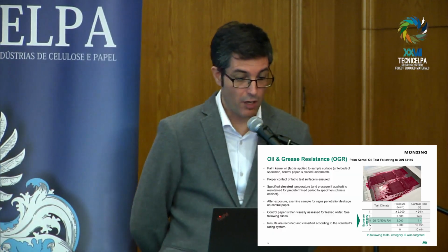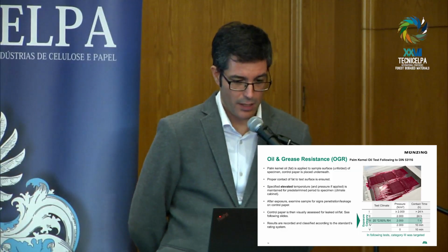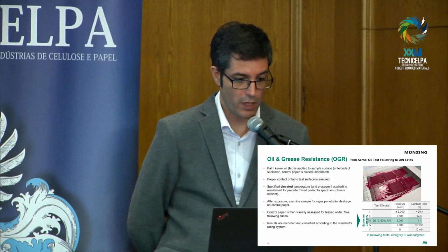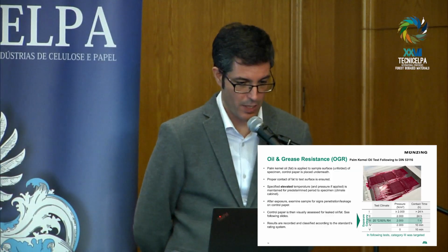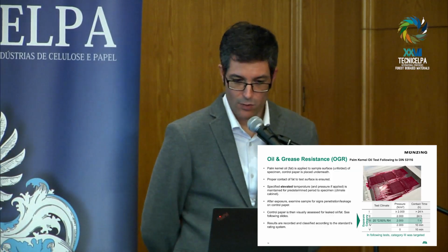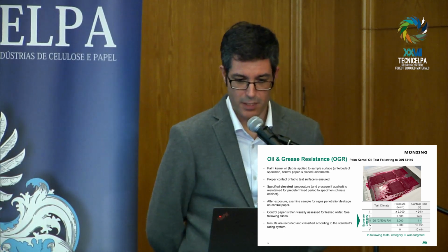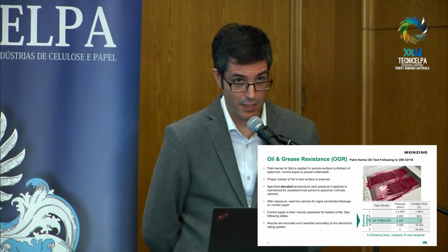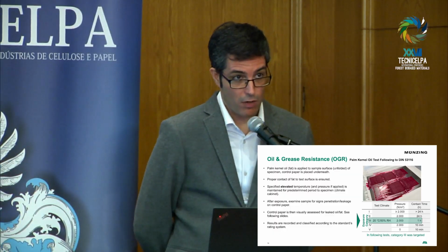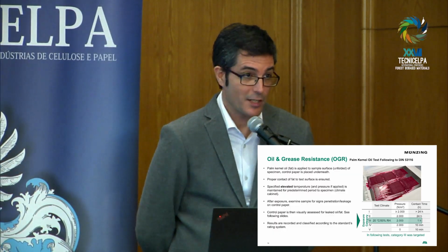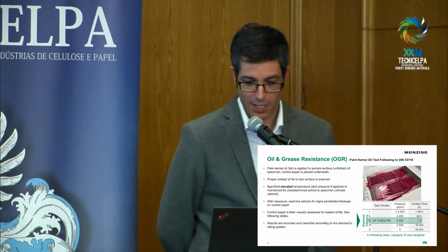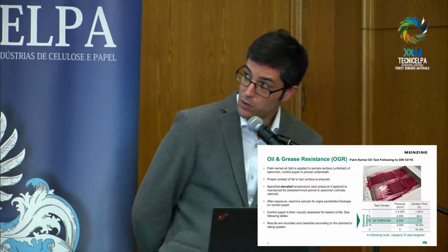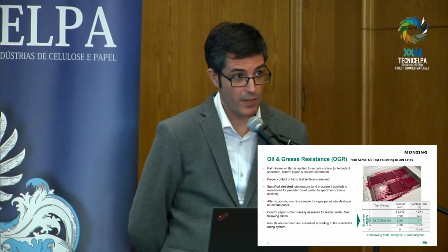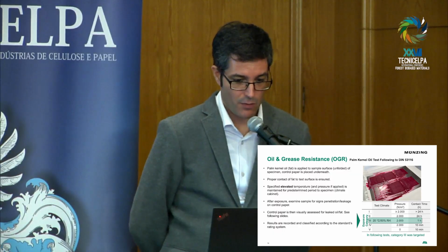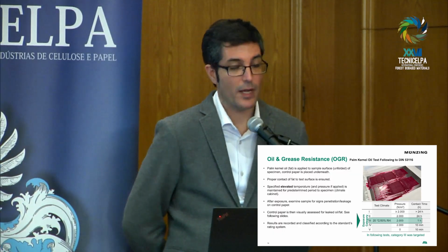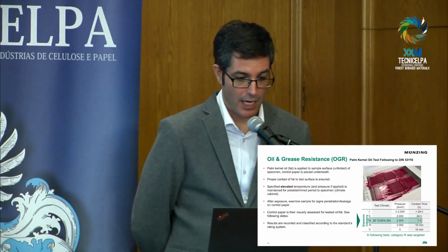Second test was the oil and grease resistance. In that case, we didn't take the kit test option, because we know that the industry is moving away from this method because it's not really realistic, and we decided to do the palm kernel oil test. This is based on the DIN 53116. This is a very common oil in all the kitchens, probably not in Portugal or in Spain, but in other countries. So we applied this in these small 5 windows you can see in the image. The excess of the material was removed, and then this paper sheet was pressed within 2 plastic sheets and put in a climate chamber.